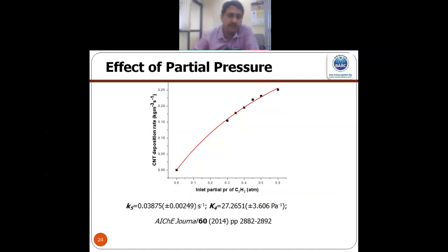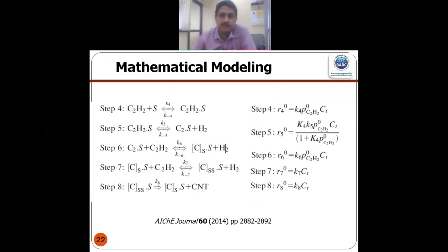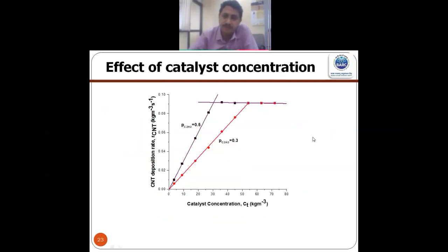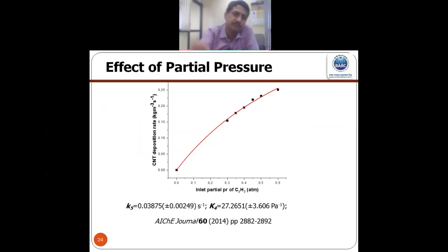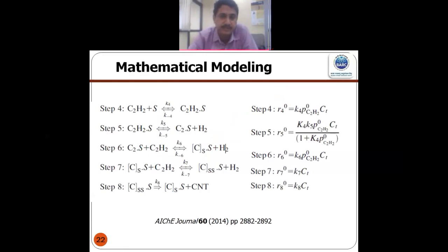Now we change the partial pressure. When you change the partial pressure, you see that the carbon deposition rate follows a particular trend. And which is that trend? We need to plot all these equations with respect to that plot, and we could see that the equation related to step 5 is exactly matching with the experimental data points. So we can see now that step 5 is the rate controlling.